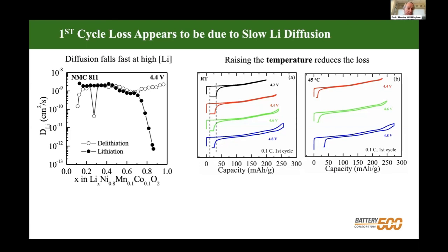So we want to check that diffusion was really the issue. We still don't know whether it's diffusion in all the bulk of the material or in the surface layers. But if we look at what we typically do, charging these materials to different voltages, you'll see we got the first cycle loss in every case, whether it's 4.2 volts or 4.8 volts. You'll see with the standard carbonate electrolytes, there's a big spread at 4.8 volts between discharge and charge. We're getting surface reactions and resistive films on the surface. A little bit in the green one at 4.6 volts.